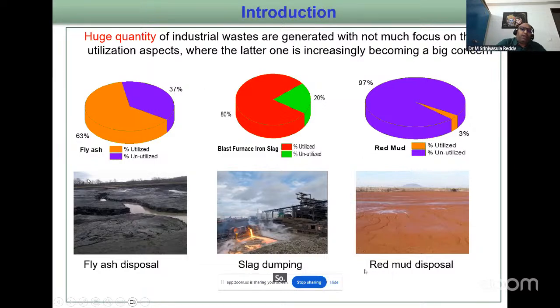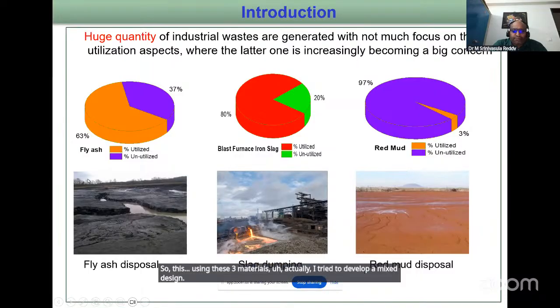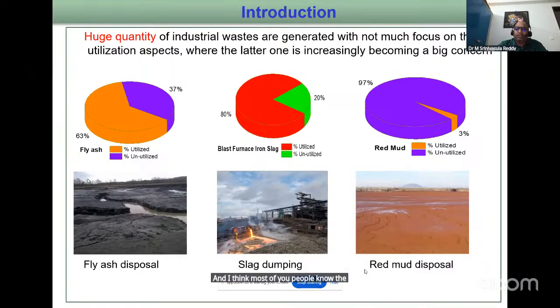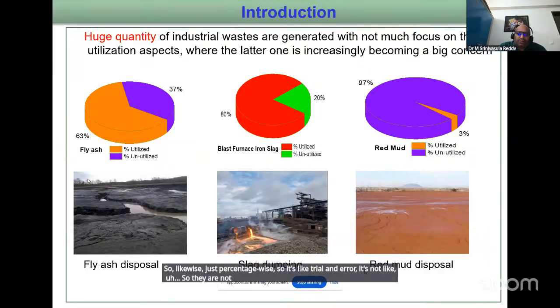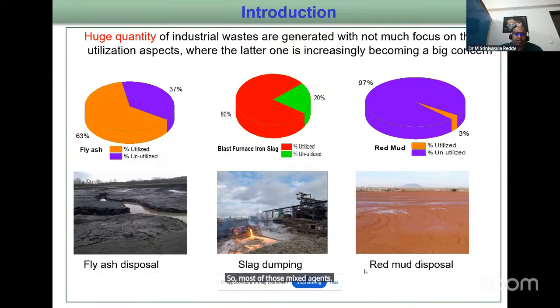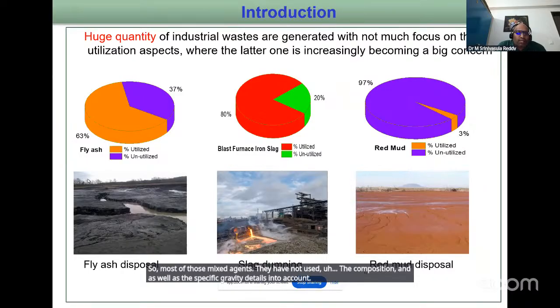So using these three materials, I tried to develop a mix design, and I think most of you know the mix design. Different researchers have proposed different mix designs, and prior to starting my research on this, I found many are using only the trial and error method, like by considering 70% aggregate and 30% as binder material. So likewise in this percentage wise, it's trial and error. They are not considering any properties of the material used, or the specific gravity, or physical properties or chemical properties, we can say the oxide composition. So most of those mix designs did not take the composition as well as the specific gravity details into account while developing their mix design.